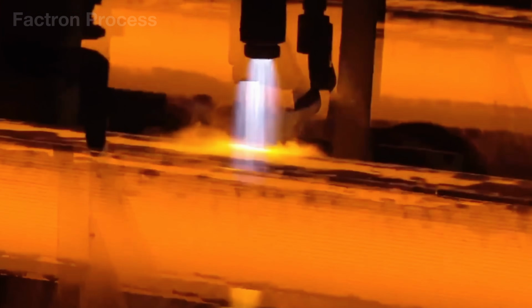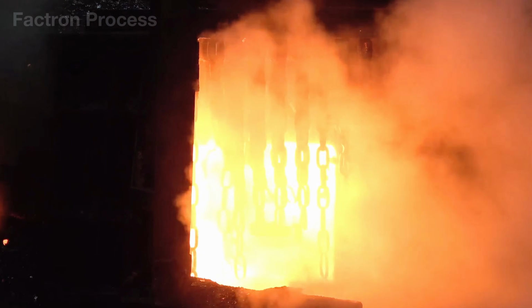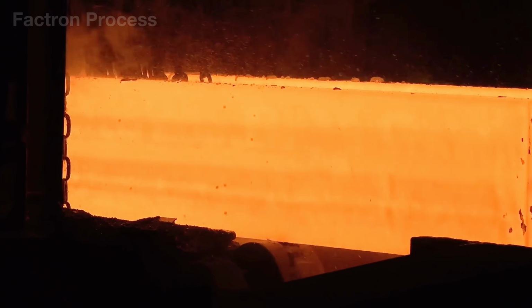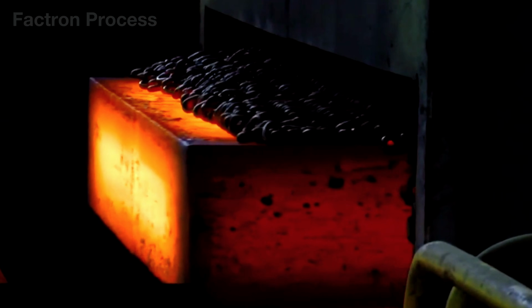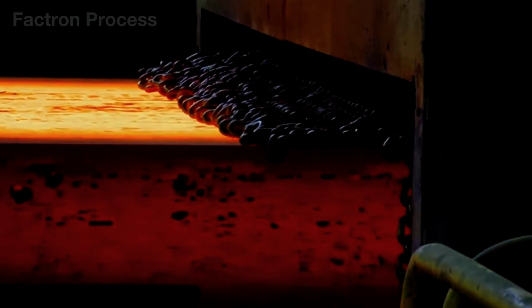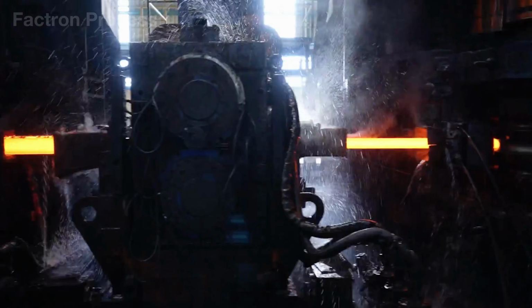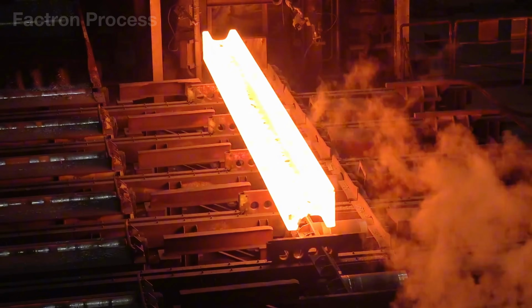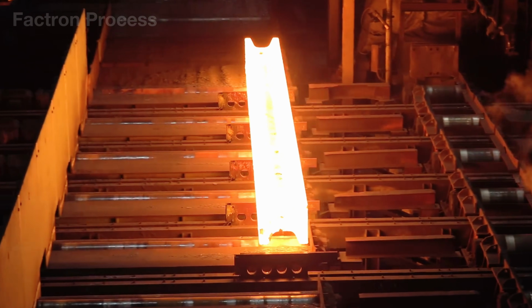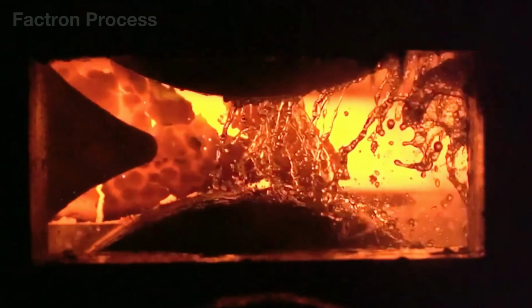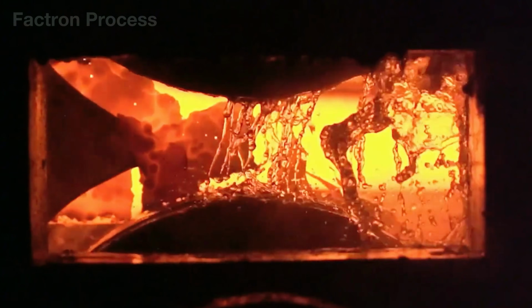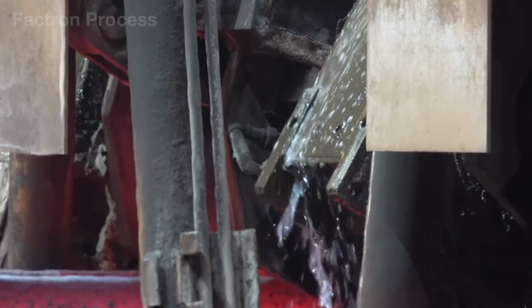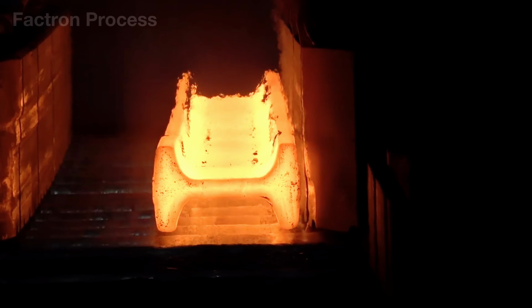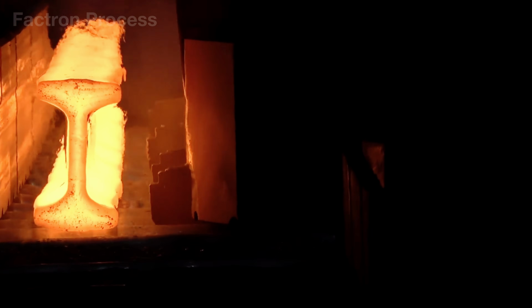These hot blooms are immediately charged into a walking beam furnace, where they are heated evenly to 2,190 degrees Fahrenheit in preparation for the next stage. Leaving the reheating furnace, the glowing steel blooms race directly into the hot rolling line. First, they pass through a high-pressure water descaling station operating at approximately 3,190 psi, blasting away the dirty iron oxide scale. Traveling along the roller table, each bloom enters a reversing roughing mill.